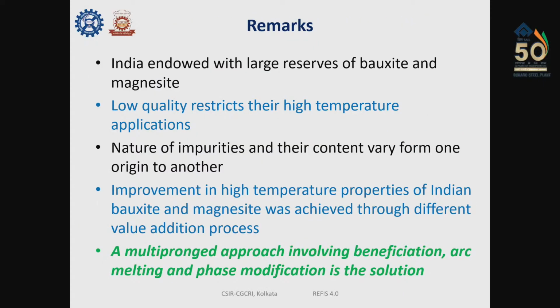So, in my remarks, I mentioned that India, though endowed with large reserves of bauxite and magnesite, has low quality material, which restricts their high temperature applications. As the nature of impurities and their content vary from one origin to another, there is no single point solution for this problem. So we need to tackle each and every material based on its impurity content. In CSIR, we have done some work which gave good results, but again we need to go further. As a result, we need a multi-pronged approach involving beneficiation, arc melting, and phase modification in totality, so that we reach our solution, so that Indian magnesite and bauxite can be used for high temperature applications. Also, co-development is the key to tackle this challenge. Thank you all.